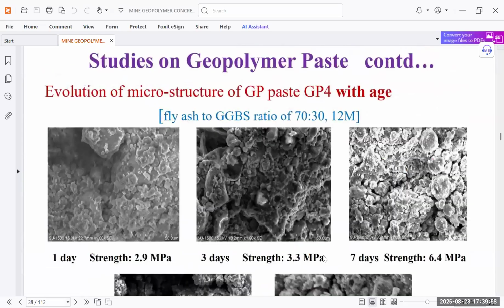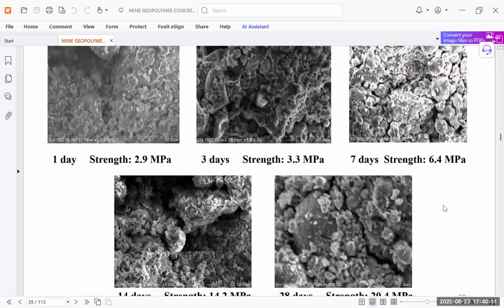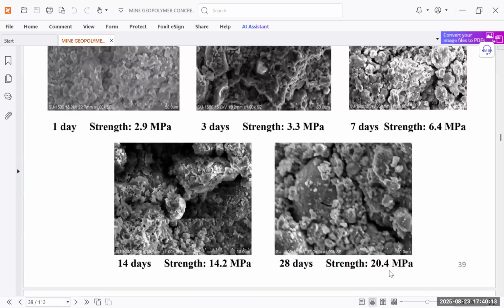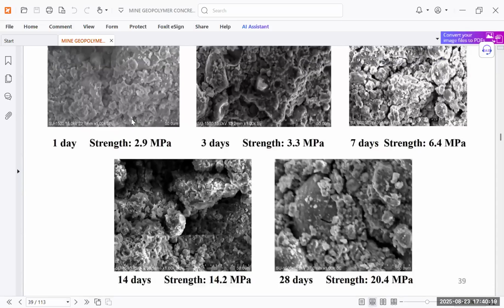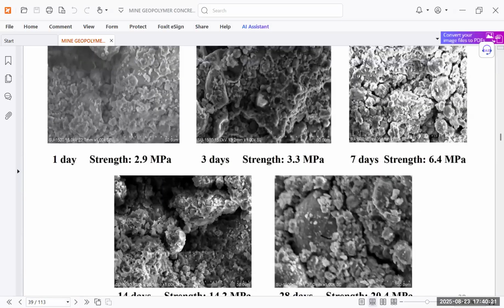So these are the 3 days strength, 3.3 megapascal, and we have taken these pictures at the micro level. This is the 7 day strength, 6.4 megapascal, and after 28 days the strength is 20.4 megapascal. You can see how the strength goes up over different days, as in the case of RCC also. So by this we can understand that geopolymer concrete also produces results similar to normal concrete,